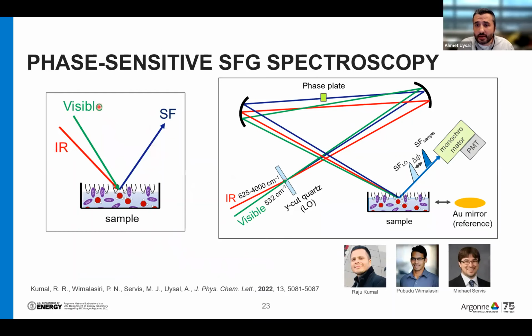This is a classical SFG experiment where you use two lasers and get your SFG signal. In phase-sensitive SFG, we generate a sum frequency signal from a Y-cut quartz, and then we generate another sum frequency signal from our sample, and we interfere them by controlling the delay between these two signals. That interference allows us to determine the phase from our sample, and basically it gives us the phase information and the orientation of these molecules.